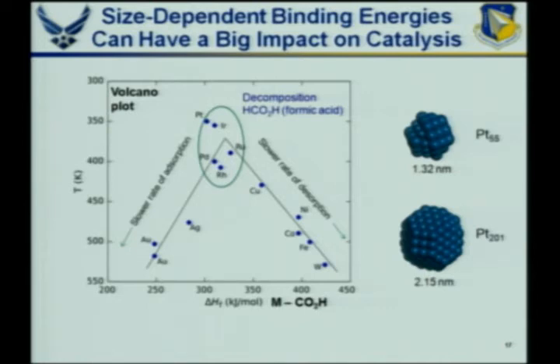And the reason that's very interesting is when people talk about catalysis, they often use this construct called a volcano plot. And that says that in order to have catalysis, you have to have something that binds to the catalyst. So if the binding energy is small, you don't get much catalysis. But if you bind too strongly, then it never leaves the catalyst, and the catalyst gets poisoned, and those active sites are gone. So you need something that's not too weak, not too strong, something in the middle. And if you plot binding energies, you get this peak, the tip of the volcano. That's where you can predict what the most active catalysts are. But now, if the binding energy depends on the size of these nanoparticles, you'll have size-dependent binding energy. So for platinum, we're going to have a whole separate dimension of this volcano plot. So now we're going to start to see three-dimensional volcano plots, maybe more realistic, and multi-dimensional plots. So I think that's an interesting thing that's coming out of these findings of size-dependent binding energies, and ways to be able to predict what sort of reactivity is going on.